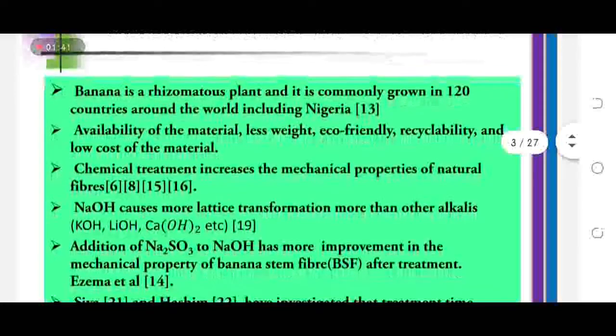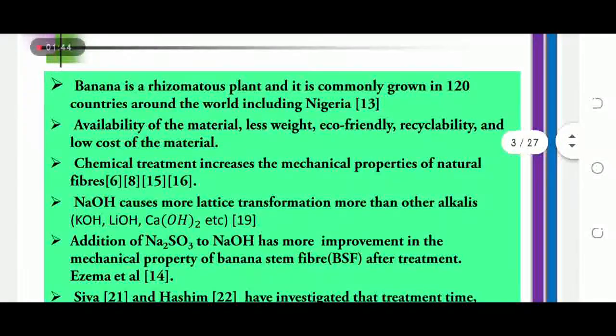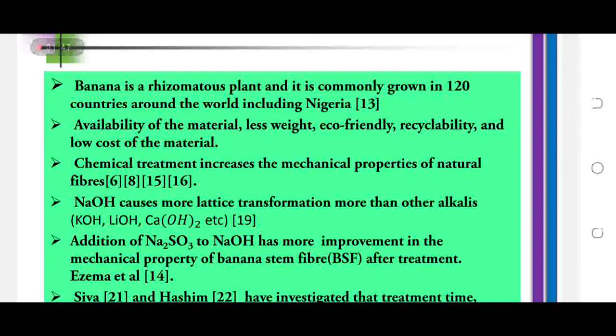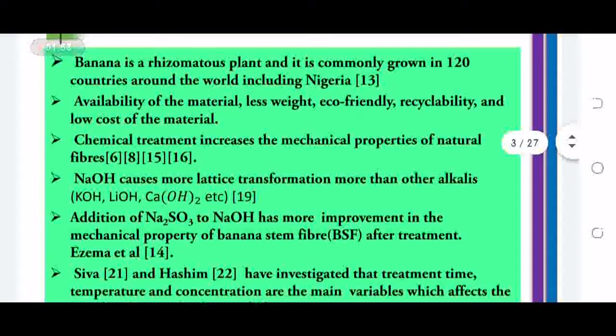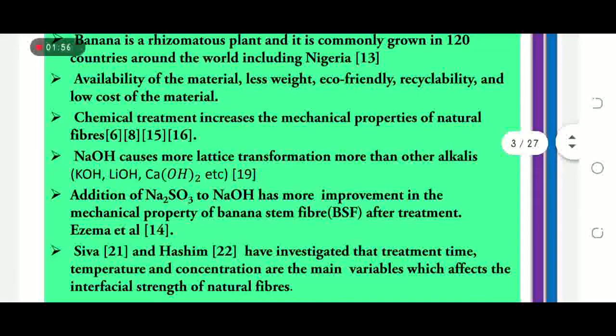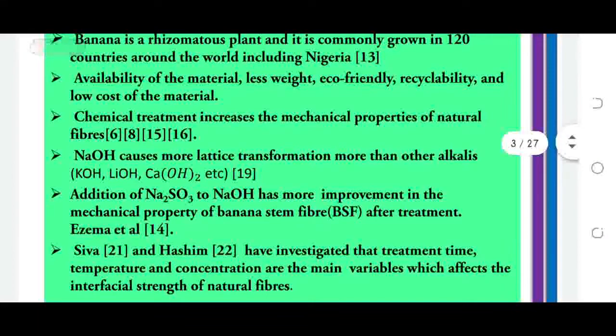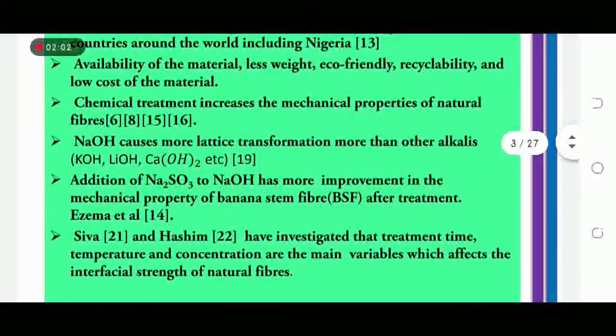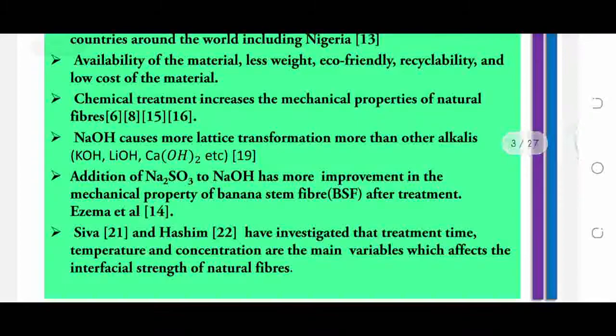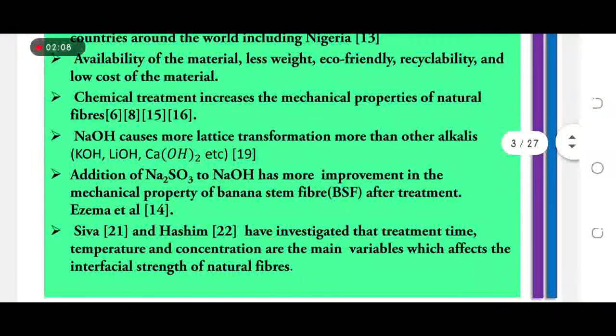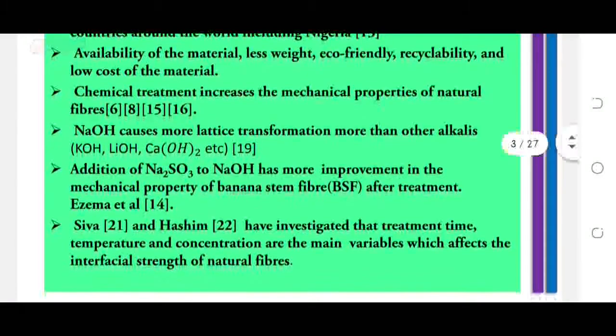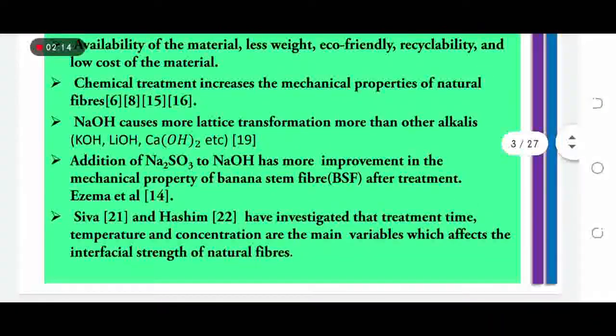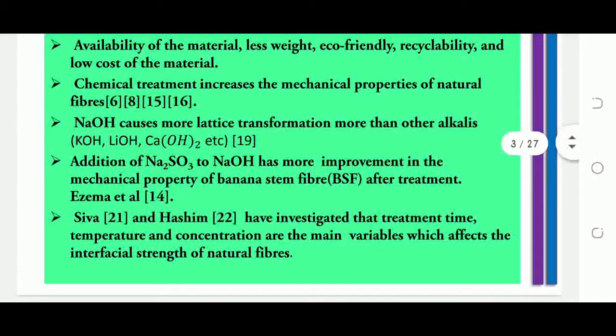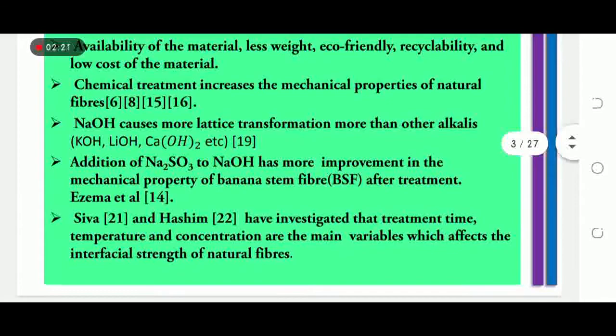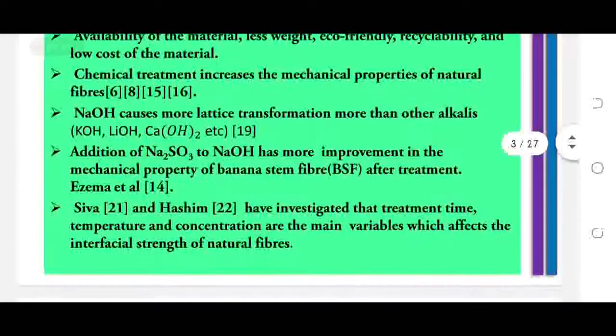Banana is a rhizomatous plant and is commonly grown in 120 countries around the world, including Nigeria. It's available all year round and is eco-friendly and can also be recycled, and it's also a low-cost material. So it has been established that chemical treatment increases the mechanical properties of natural fiber. Now, sodium hydroxide causes more lattice transformation than other alkalis such as potassium hydroxide, lithium hydroxide, calcium hydroxide, etc. Now, in the separate research done by Ezema et al., we found that addition of sodium sulphite to this sodium hydroxide had more improvement in the mechanical properties of the banana stem fiber after treatment.